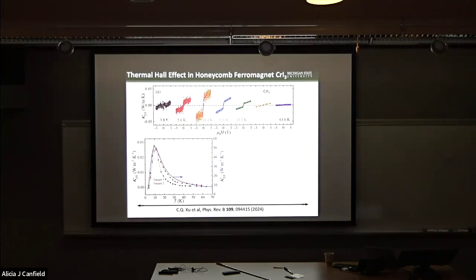It shows the field dependence of the thermal Hall signal of this compound measured at several different temperatures. And then again, from this data, we will extract the temperature dependence of the thermal Hall conductivity. Right? And here, again, related to Martin's question, we made multiple samples. Here I just show two. You can see that the behavior of these two samples is very comparable to each other.